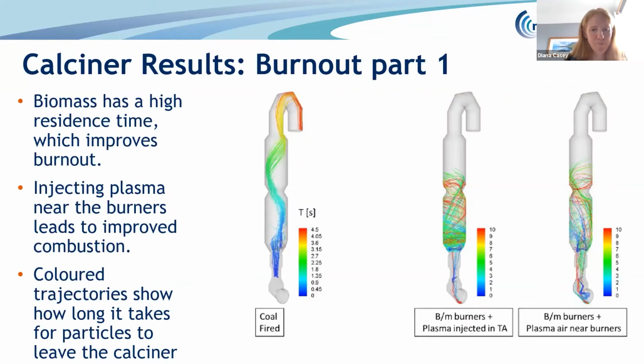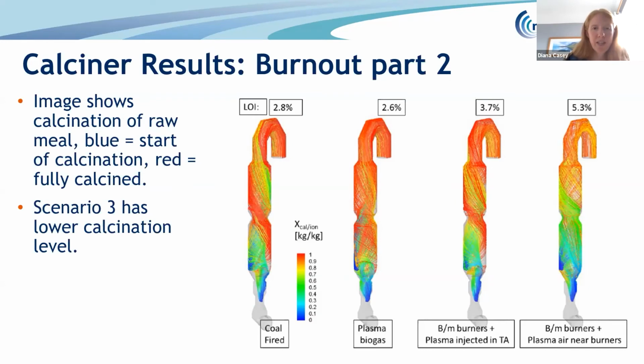This time, the images show the calcination of the raw meal. The blue end of the scale shows the start of the calcination, and the red shows the fully calcined material. This time, all three fuel switch scenarios are shown because they've all got the raw materials going into the calciner. In this case, scenario 1, using the biogas, leads to greater calcination. You can see there's a lot more red in there than in the other scenarios, and scenario 3 had the lowest calcination level.